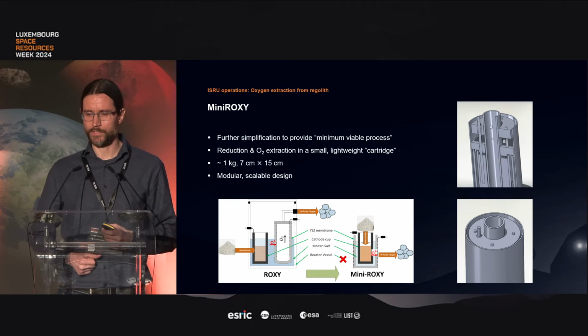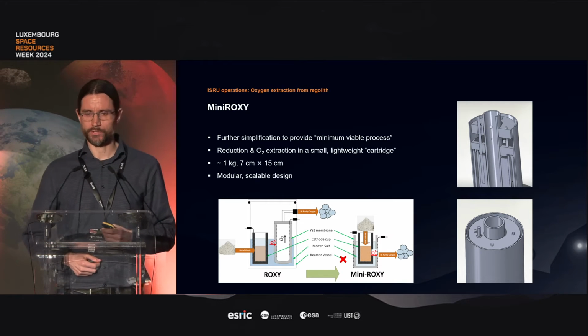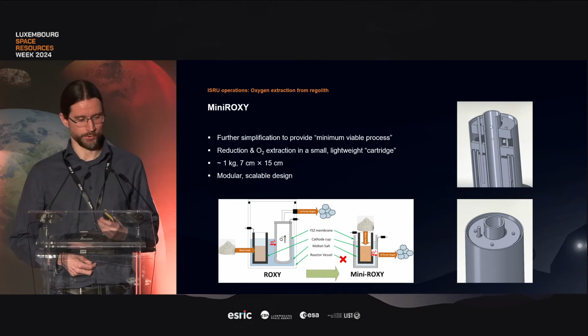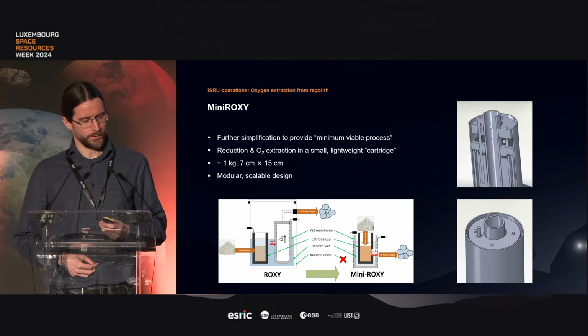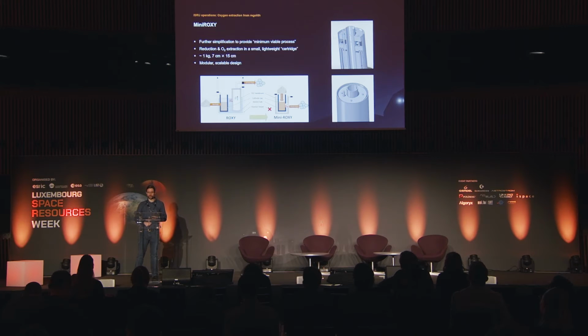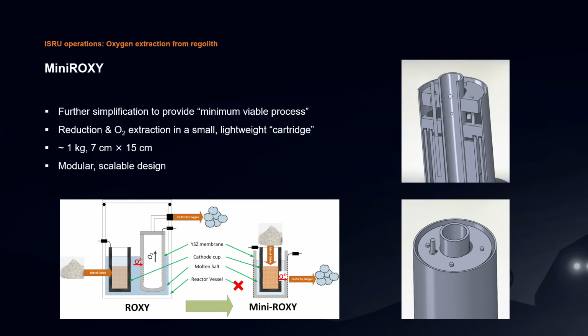Mini-Roxy represents a further simplification and miniaturization of this process to provide something of a minimum viable demonstration. As you can see in the image on the bottom, the main difference to the original Roxy process is that the reactor vessel is removed and the zirconia membrane now also acts as a reactor vessel. This has some advantages in material compatibility, but also significantly reduces the size and the mass of the system. And it means that in a relatively lightweight so-called cartridge, which is shown on the right-hand side, we can perform the reduction and the extraction of oxygen.